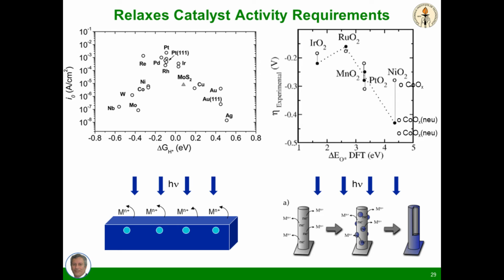Based on these low overpotential earth-abundant catalysts for the hydrogen evolution reaction, we can take advantage of another feature of the microwire array, and that is that the photon flux from the sun on a planar surface has to pass the corresponding set of charges back through the entire plane. But as you can see in the right, in the lower panel, on a microwire array, that same solar photon flux produces a much lower catalyst demand because the flux is distributed across the internal area and volume of the microwire array instead of being forced to come up through the projected area of the sample.